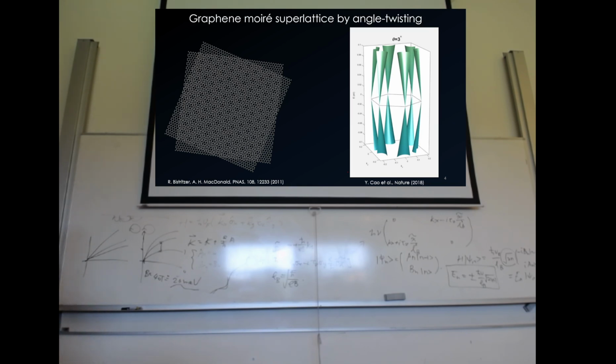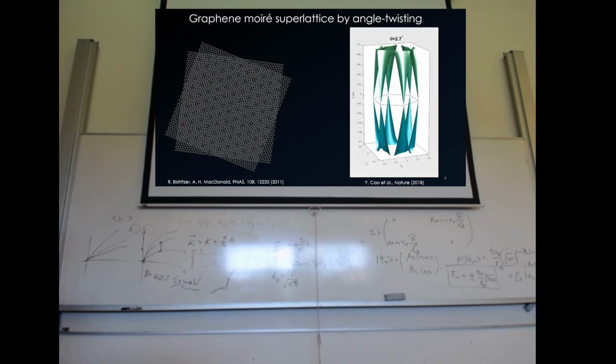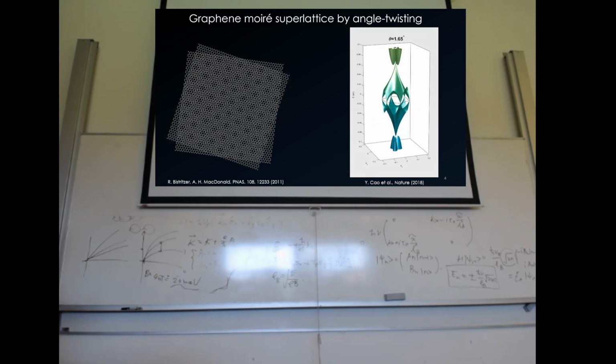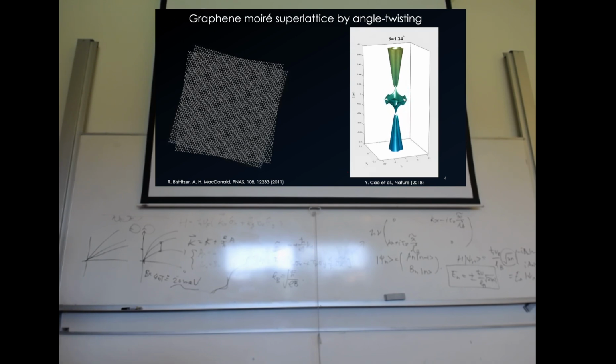Let's look at this twisting again. Before, in the previous session, I showed you the twisted model between graphene and hBN, which has a lattice constant mismatch of 1.8%. Now if we have two sheets of graphene, imagine we forget about relaxation or deformation. In the ideal case, you have zero lattice mismatch, and there is also a moiré showing up in the system. If you twist them and diminish the angle from large to small, at some point the band is squeezed and flattened out. At 1.1, there is a tiny gap between the dispersive band and the flat band. So it's gapped, possibly because in this scenario the symmetry is different. You can create symmetry breaking through C2z symmetry breaking. You can also create Chern bands, which are topologically non-trivial. But at least with this, we can see that 1.1 is the first angle when you approach from large twist to small twist angle.